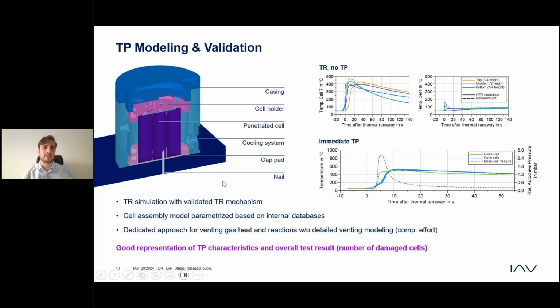If we look here at the validation, as mentioned before, we built a model of the module, having also the nail and the 7 cells and the gas in between the cells, so it's a CHT approach here, and we have also all the different parts of the module represented here. And if we look, for example, at this case, we have the comparison between the CFD and the measurement. The measurements are the dashed lines, and the CFD simulation are the straight lines. We can see that for the thermal runaway of the central cell, we have a good match between measurement and simulation. This is a result after the calibration that Kislaya just showed us earlier.